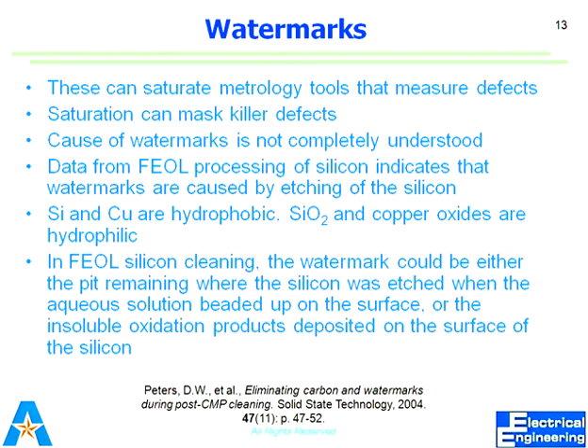you need to be careful that water marks are never there. Water marks can be there due to many reasons, but the exact reason why the water marks are there has not been completely understood. Some people say there may be some pits on the surface and water stays in there, and some say that water etches away the part where it stays. But watermarks are one of the contaminations, and you always consider that there should be no watermark if you want your wafer to be considered a clean surface.